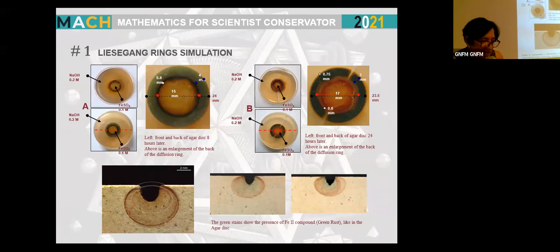An interdisciplinary study, both experimental and numerical, was performed here, where I was responsible for the experimentation on porous host materials. The first on a petri dish filled with colloidal agar gel solution and sodium hydroxide, while a second experiment was performed using Lecce stone as the host material. Both materials were placed in contact with an iron source to produce the rings.